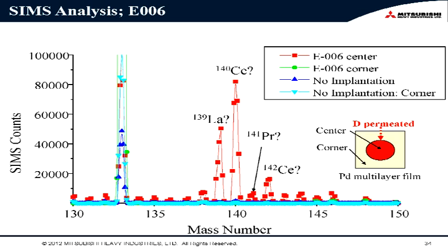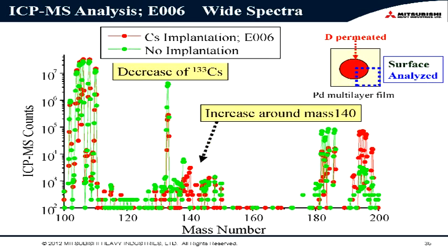And to confirm this result, we performed ICP-MS analysis. ICP, inductively coupled plasma mass spectrometry, to confirm this result, because SIMS is a analysis for a point. So if we analyze this sample, we also get similar results. We can see the decrease of cesium-133 and an increase around mass number 140 for surface analysis.